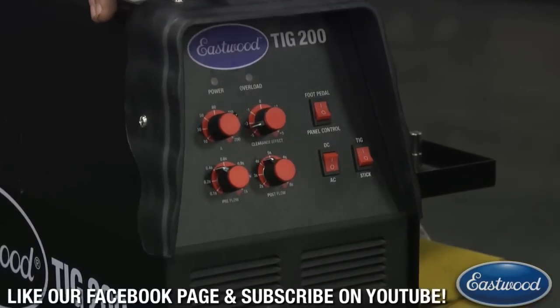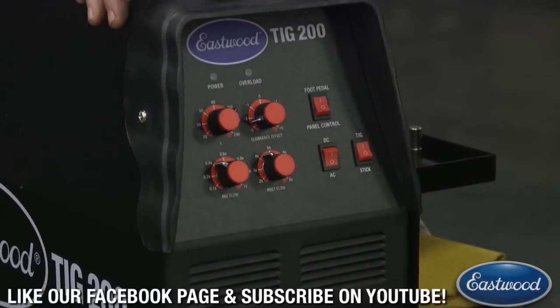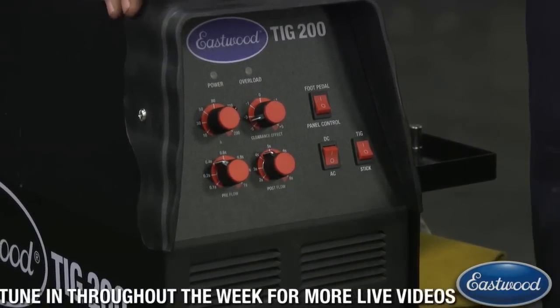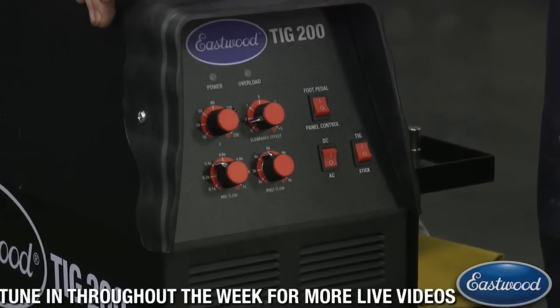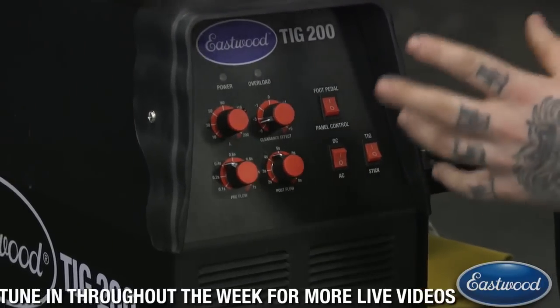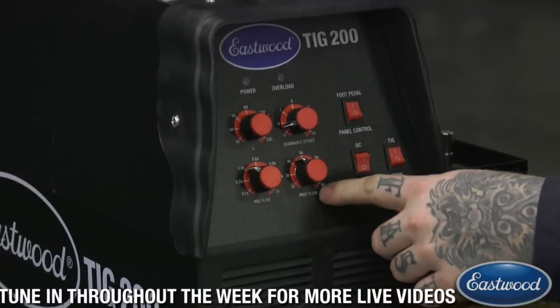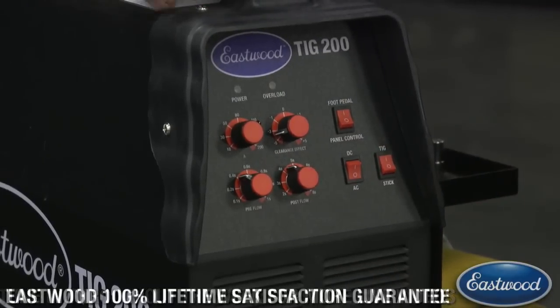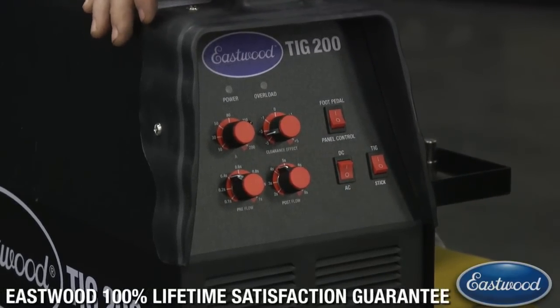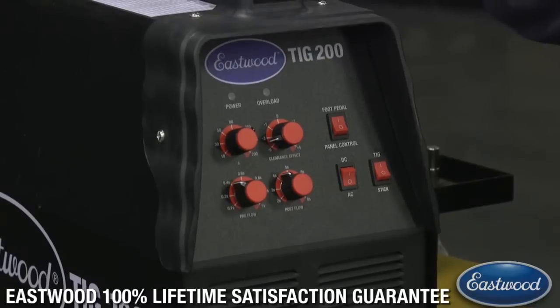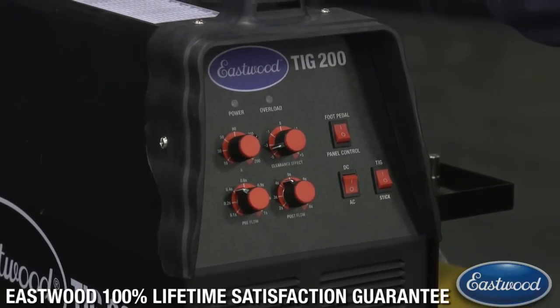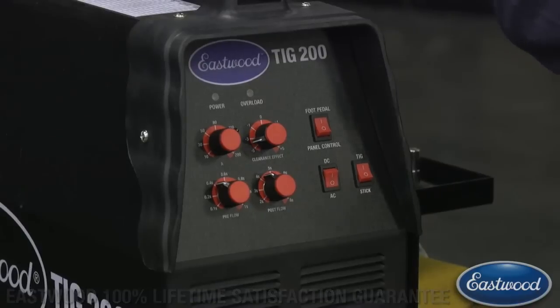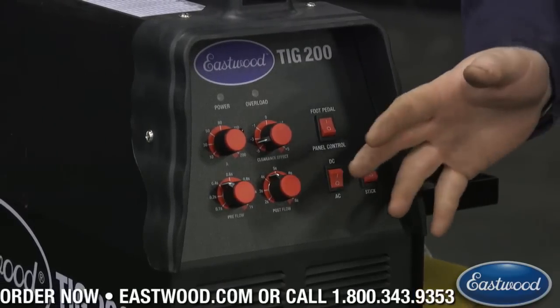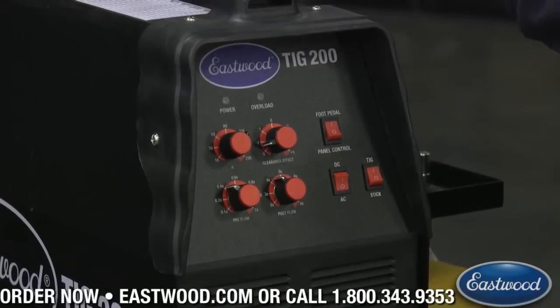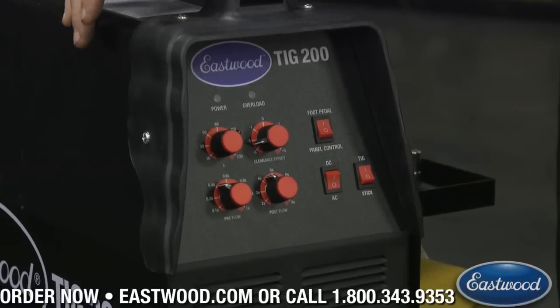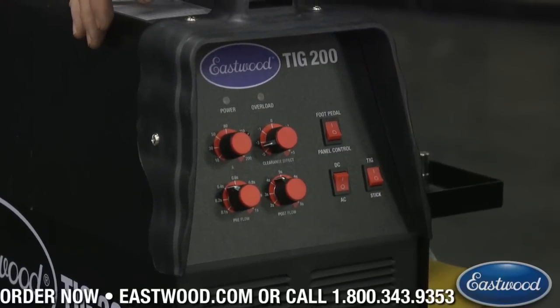That's so we have some additional gas flowing over top of our weld before we initiate an arc, to give us an extra little bit of clean area to work. We have the post flow here. I also have that turned up to about 4 seconds. Again, with aluminum, it's more susceptible to cracking or to having contaminants get into the weld after you are done welding. So I like to have the post flow a little longer than I would for steel. I have that set at 4 seconds.